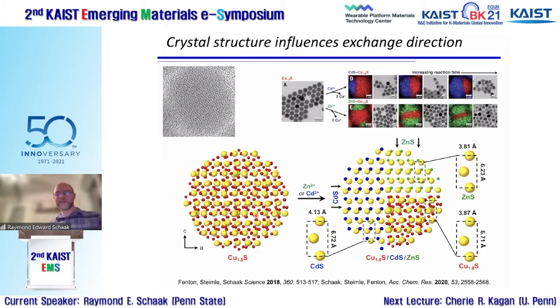And so that's exactly what happened. So for cadmium sulfide, without going into all the numbers and the details, I'll keep this a little more high level. Cadmium sulfide interfaces best with copper sulfide along this crystallographic direction. As you might guess, zinc sulfide has a smaller lattice constant. Zinc is smaller than cadmium. So if cadmium's happiest here, it's pretty unlikely that zinc also would be happy in the same crystallographic direction. So for zinc sulfide, when you do a cation exchange, it prefers this crystallographic direction to interface with copper sulfide.